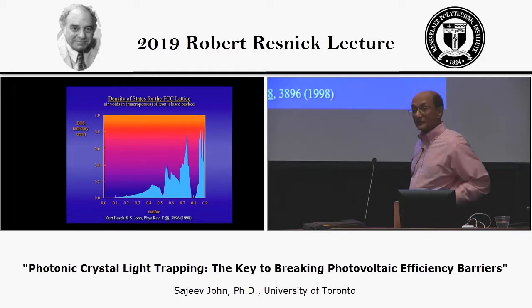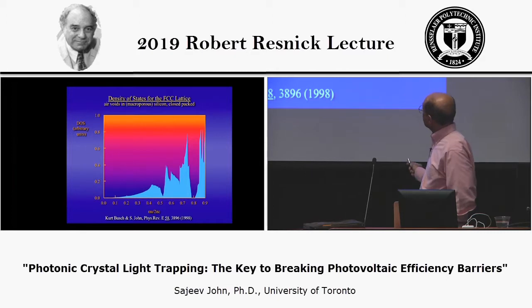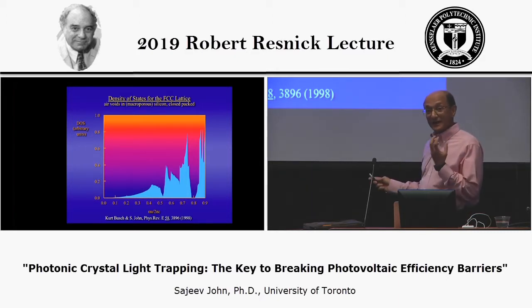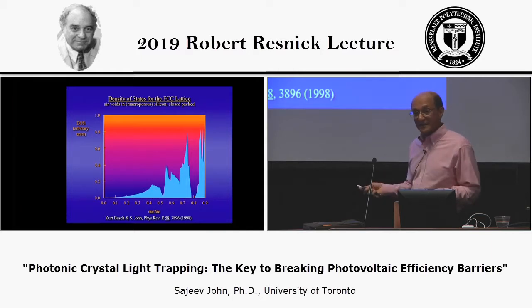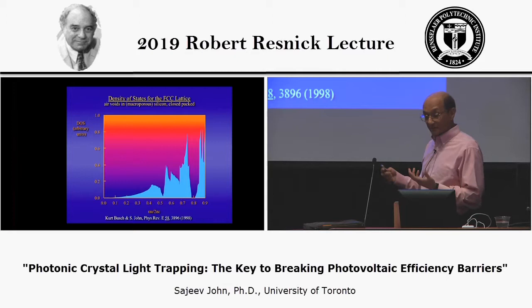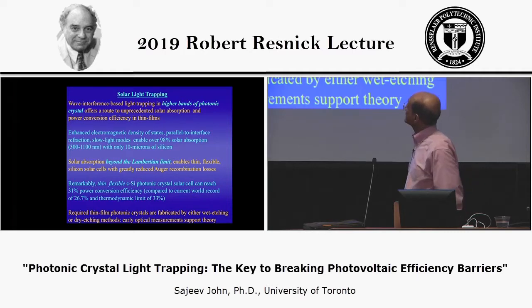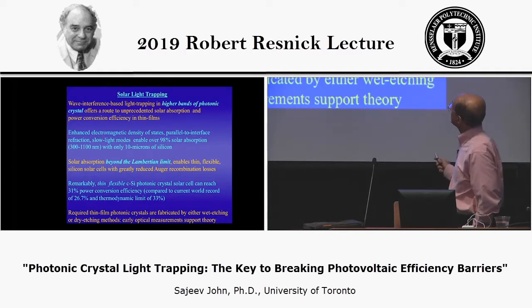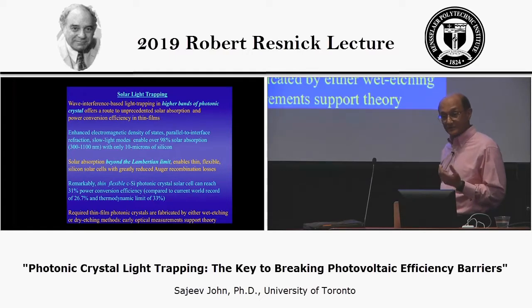And in the case of photovoltaic light trapping, the action that I'll be focusing on is in these regions where there is a very high density of states, where you can get a different type of light trapping due to slow light modes, as they're referred to, in which the light is bouncing around inside the structure and remaining there due to wave interference for absorption to take place, even though the absorption is intrinsically very small. So what I'd like to show is that wave interference-based light trapping in the higher bands of a photonic crystal offers a route to unprecedented solar absorption beyond the Lambertian limit, and as a result, higher power conversion efficiencies than have been demonstrated in real solar cells so far.